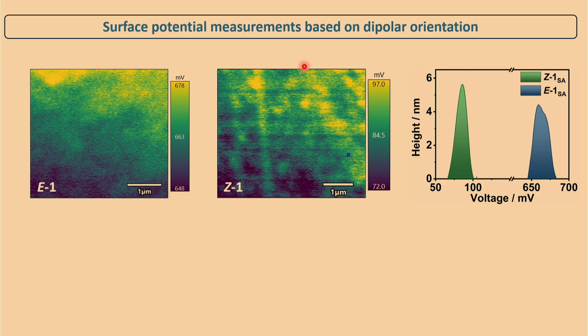And the last thing, this is what we do always. We have not yet tried the piezoelectricity of such fluorinated azobenzene in the peptide, but we looked at it with our Kelvin probe. What you do is take the AFM tip, touch the surface, connect the circuit and see what the surface potential is. In this particular case, in the trans form you have a very high surface potential, around 664, but in the case of the cis form you have much lower, 84. So the structural orientation changes the electrical property. That is what we believe. The changes in piezoelectricity over this switching will also be quite dramatic.